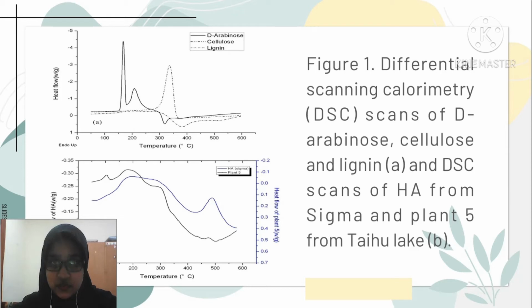For the cellulose, there were only 2 peaks observed, which is an endothermic peak at 336.2 Celsius and an exothermic peak at 378.6 Celsius. Lastly, the lignin exhibited 2 endothermic peaks at 205.4 Celsius and 278.0 Celsius, and also an exothermic peak at 384.4 Celsius.